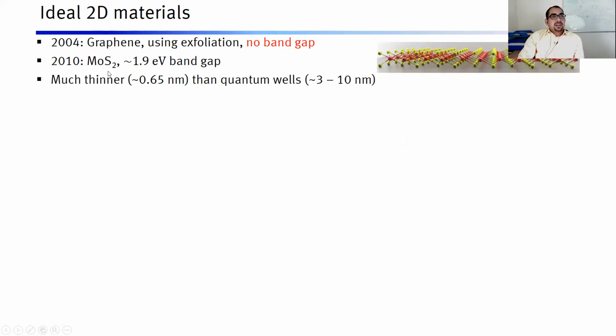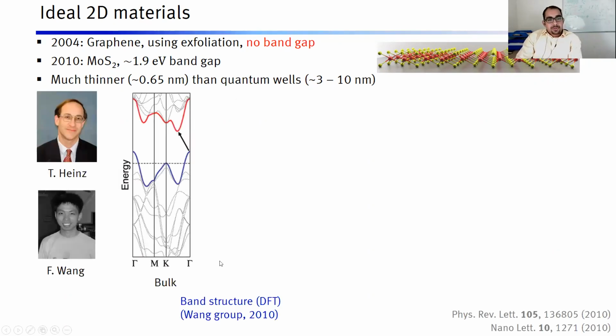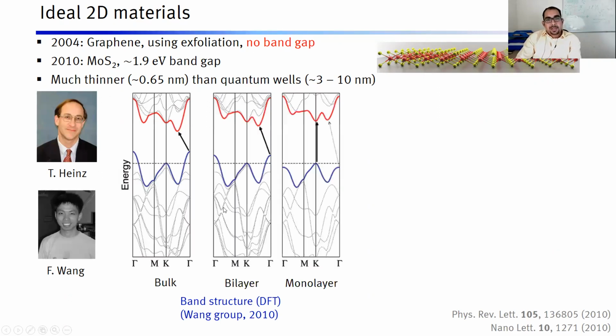However, in 2010, MoS2 was exfoliated. A single layer of MoS2 has a band gap around 1.9 electron volt, which lies in the visible region. It's much thinner than the quantum wells, and it's an ideal 2D material now. Most interestingly, the band structure is indirect gap in nature for bulk, but once you reduce to monolayer, it becomes a direct band gap material, and it starts to emit very brightly.